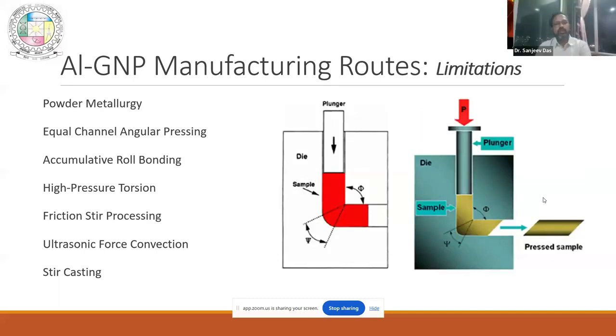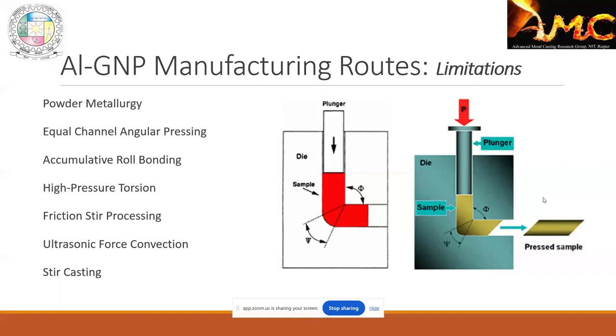Next is basically the equal channel angular pressing. Here what you do is you are basically mixing these materials in an L-type pattern, and then you use a plunger and you are forcefully bending it, and you are thinking that it's going to mix. But it's very difficult because it's a solid state process, and it's very difficult to get a uniform mixing of these particles.